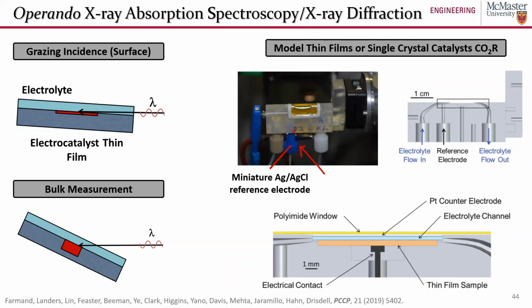You can see here, this little blue nut here is where a reference electrode went in. You can kind of see it on this diagram here. We didn't have much room to work with, so we used a 2 millimeter silver chloride reference electrode for these experiments. And this is where some of those headaches that I mentioned came from, where we found that this reference electrode wasn't as reliable as we would like it to be. But really, because of our space restrictions, we had no better options. And so we were like good little scientists. We made sure we calibrated, and we did a lot of sanity checks on those materials to make sure that the electrochemical potentials we were measuring and reporting were reliable.